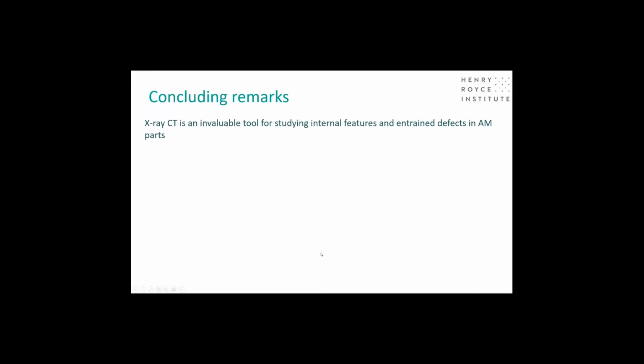Okay, so I've given you a little bit of an introduction to the use of X-ray CT for the determination of defect microstructures in additively manufactured parts. X-ray CT is really useful because it can provide not just the external features, but the internal and the entrained defects in additively manufactured parts. AM processing can be visualized in real time by high frame rate radiography, and a great deal of information such as the cracking that Stephen showed or the defect entrainment that I showed can be picked out from real time radiography at many thousands of frames per second.